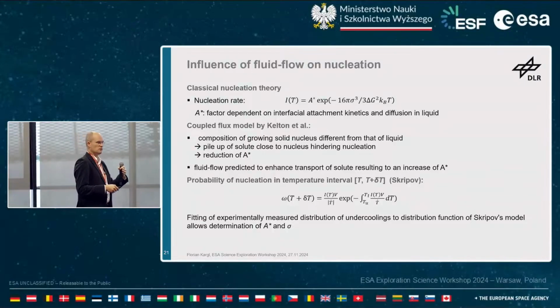However, in the systems that we are looking into now, it's not that simple, because this means that you shouldn't have a difference between, let's say, the growing nucleus and the liquid. However, in the systems that we are looking into, there's a difference between composition of the growing solid nucleus and the liquid, which means you have a pileup of the solute, and that, of course, impacts on the nucleation rate. And there's a coupled flux model by Kelton to describe this, and this works pretty well, as we can see in the data later on.